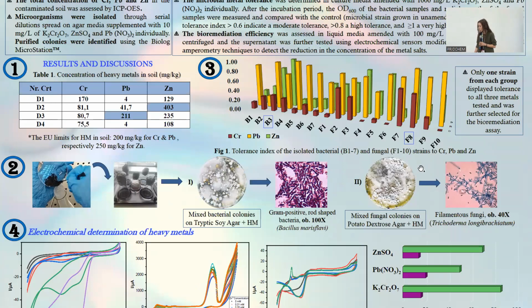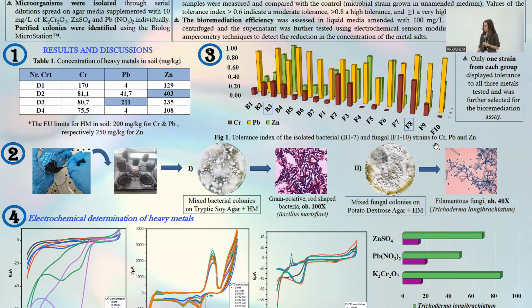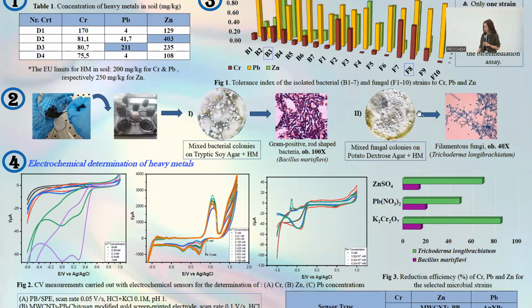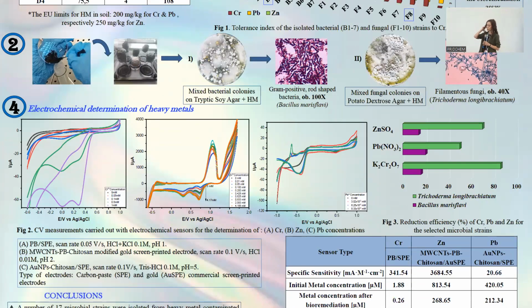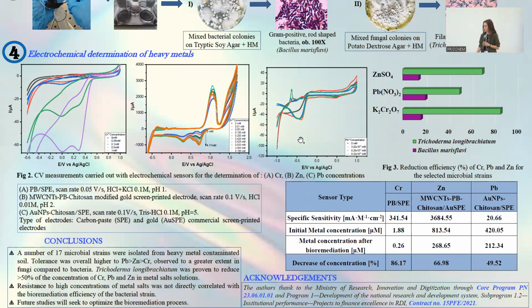We have further selected 1 strain from each group that presented tolerance above the moderate level to the 3 heavy metals for the bioremediation assay. The removal efficiency was determined by comparing the concentration of the heavy metals in solution before and after the microbial treatment. These differences were detected using commercial screen-printed electrodes modified with different materials. For chromium detection, Prussian blue mediator was precipitated onto the carbon paste of the screen-printed electrodes.